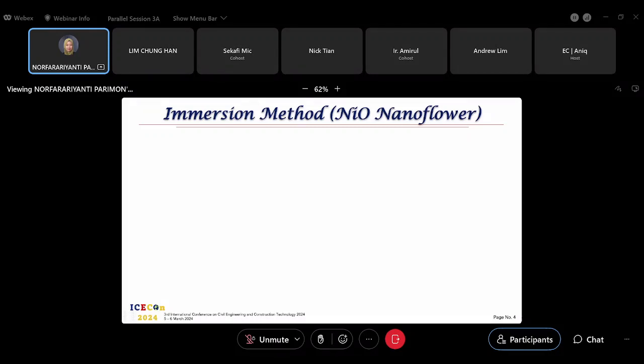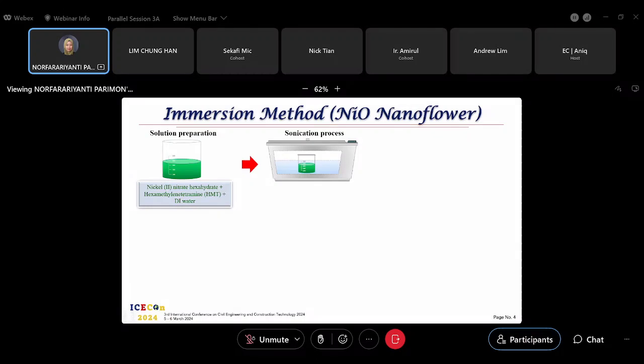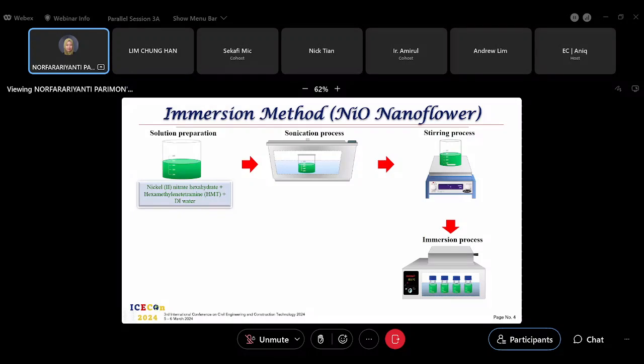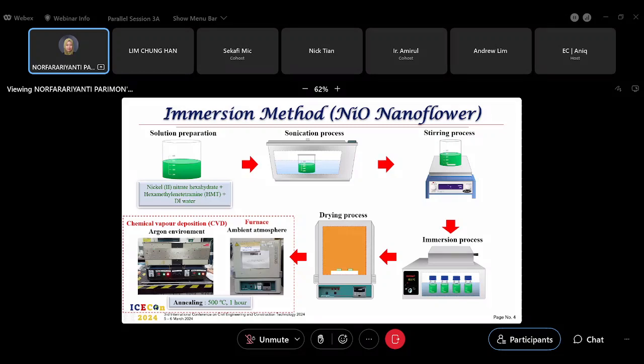The second step is using the immersion method. For the solution preparation we use nickel nitrate, HMT, and deionized water, and we go through the sonication process and stirring. The immersion process is at 95 degrees C for 2 hours in a water bath. Then there is a drying process at 150 degrees C, and the crucial part is the sample will be annealed in the CVD, chemical vapor deposition, and the furnace.